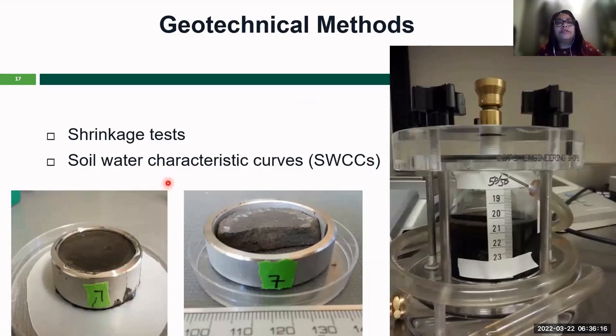It was interesting for us to look into the shrinkage test, starting with the slurry material in rings and allowing it to dry at natural air temperature and environment, room temperature, and then taking the measurements of height and diameter of the material over a period of 4 months. Continuous readings were taken, and then we also used a Tempe cell to look into the soil water characteristics. And we used suction values up to 500 kPa. Again, the measurements were taken for up to 5 months, when there were no changes continuously for several weeks, and we stopped the test.